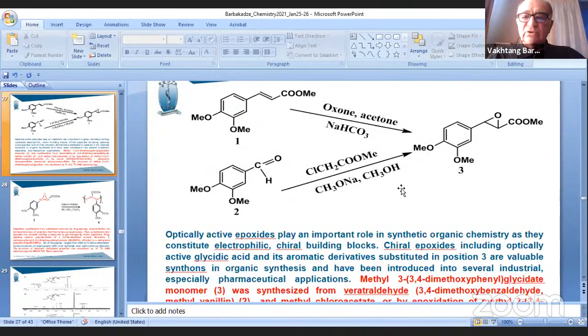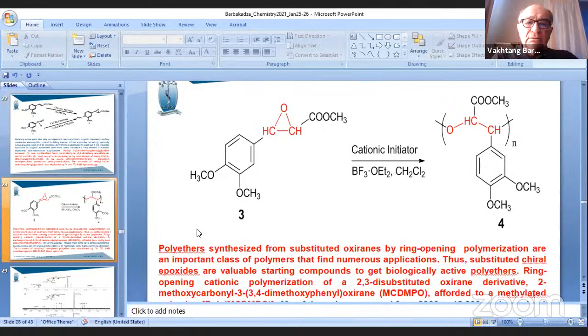Then we tried to get the epoxide as a starting compound for further polymerization by ring opening polymerization, and to get a synthetic analog of the natural polymer. Afterwards, we took the methylated epoxide of the starting compound using a cationic initiator, boron trifluoride etherate. We got, by ring opening polymerization, a methylated derivative of the natural polymer.